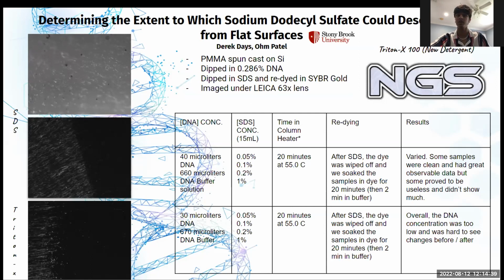We used a column heater that has the potential to completely desorb the DNA, and we kept increasing the temperature, getting closer to that 90 degrees Celsius point, which would completely denature the DNA. So we approached that, but we never crossed it. And additionally, a new detergent, Triton X, has produced promising results in desorbing DNA. It quickly created a highly visible border between the Triton X and DNA in the first try, as the bottom image shows. And the magnitude of efficacy of Triton X warrants the need for future research.